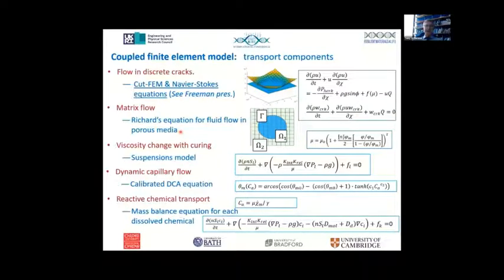Okay. Matrix flow, fairly standard Richards equation, but we have to take account of viscosity changes. I mentioned viscosity changes, so there they are. We've used various models. I've highlighted something called Einstein's suspension model here. Dynamic flow, capillary flow, when that happens, it's fast enough that the meniscus angle changes, so we need to take account of that. And there's the capillary number where the velocity term sits there. And we've also, over the last year or so, put in a reactive chemical transport so we can model a wider range of processes. Okay, this is some of the most recent stuff we've done.